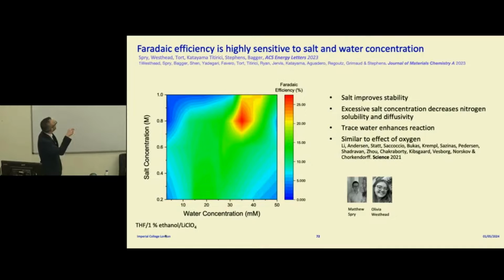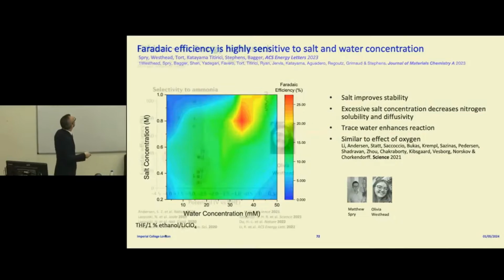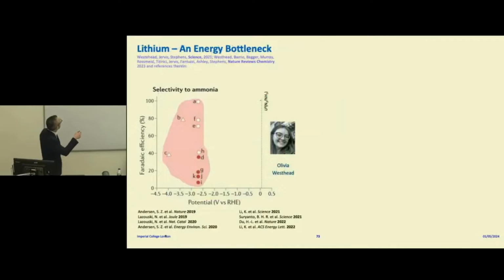So it turns out that nitrogen reduction to ammonia using electrochemistry is really sensitive. Just by changing the salt to water concentration, you can change the Faradaic efficiency, how much charge is going towards ammonia, enormously. And we're trying to find out why this is the case. But the good thing is there's been a lot of progress in the field. Now it's surpassed my own expectations. The Faradaic efficiency, how much current is going to ammonia, is approaching 100%, but there's still a big bottleneck. The potential needed, the push required to get the reaction to work, is enormous.